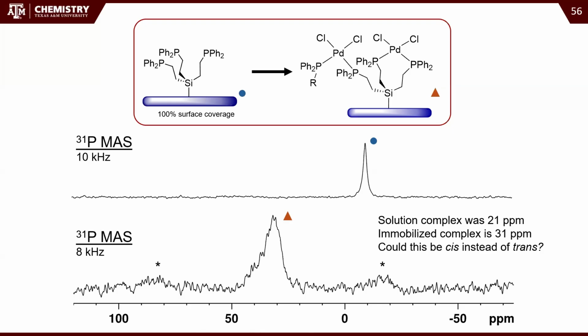You might note that the solution palladium complex was at 21 ppm, and these surface complexes are at 31 ppm. Well, why is there a difference, right? We want to make sure that this is not a surface interaction, because that kills the catalyst. So we thought, okay, it's about a 10 ppm shift. That might match the difference between having a cis complex and a trans complex, right? If we're going to make a trans complex with this, it might be a little sterically challenging to fit that